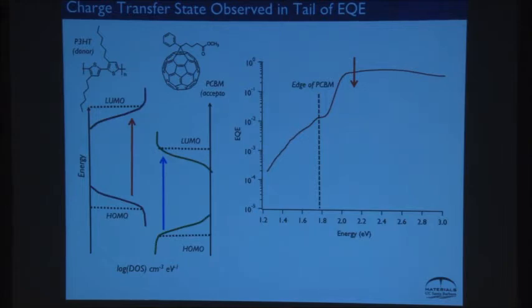But what you also see is if I plot that on a log scale, I see a bunch of tail states, right? Way out here, well below the optical gap of either of these materials, I still can generate charge. And so if I look at that, that stuff is due to basically transitions across the materials. These are interface states of the material, okay? And so every solar cell, when you go looking, you actually see this, right?